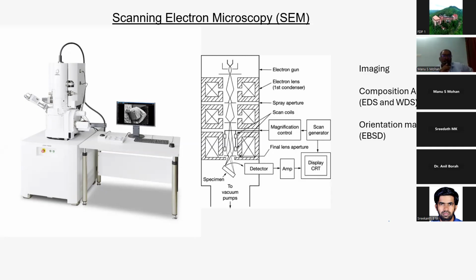So basically what happens here, you have the electron gun. In the electron gun, basically you have the filament. The filament is generally either a thermionic source or a field emission source. If it is thermionic, we generally have tungsten and lanthanum hexaboride. If it's a tungsten source, the probe size cannot be reduced much.